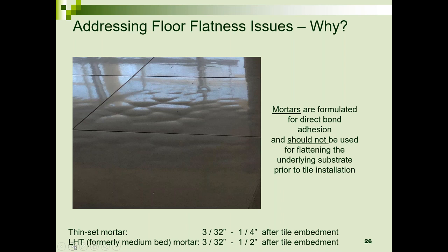Those little dimples that we see across the surface, that is mortar that has cured, and as it cured, it bonded to the bottom of the tile, and it shrank so much it pulled down and created these dimples or deflections in the surface. So the only remedy for that is tearing out the tile. Next slide.